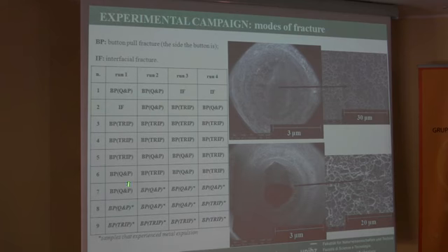And here you can see the typology of fracture encountered in the several replications according to the several tests. In particular, you can see that the interfacial fractures occurred only in the first samples. This is due to the fact that the interfacial fracture was promoted by the small nugget diameter. And then we have several button pullout fractures that occurred either on the TRIP side or the quenching and partitioning side.